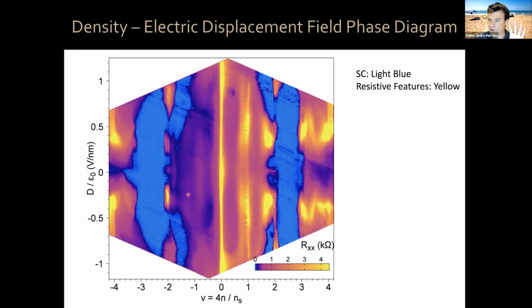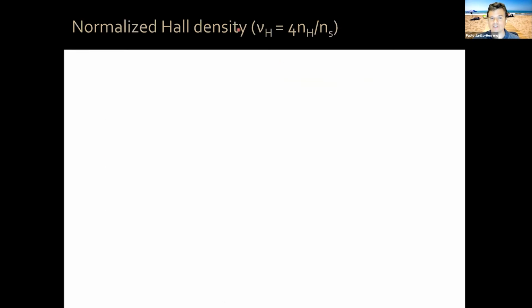Now, you could also focus on the asymmetries left to right. For example, you have resistive features here that are absent or very weak on this side. In fact, this certain degree of left-right asymmetry is very reminiscent of what happens in magic angle twisted bilayer. There is also an asymmetry between electrons and holes from charge neutrality. Now, we can measure other quantities in the system and see if they correlate with the superconducting regions. So in particular, we decided to measure the normalized Hall density, nu H. This is the Hall density equivalent of the filling factor of the regular density.